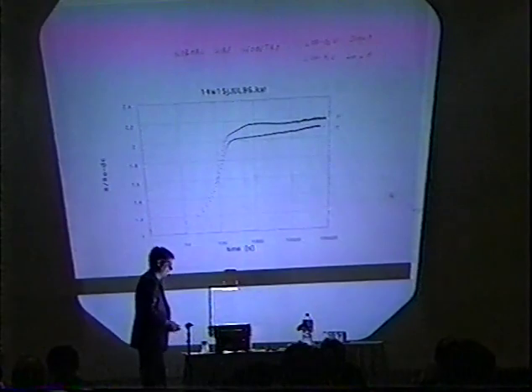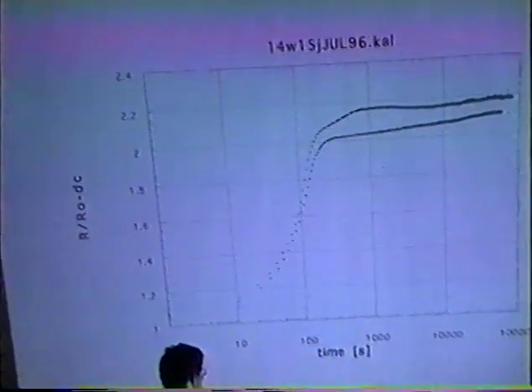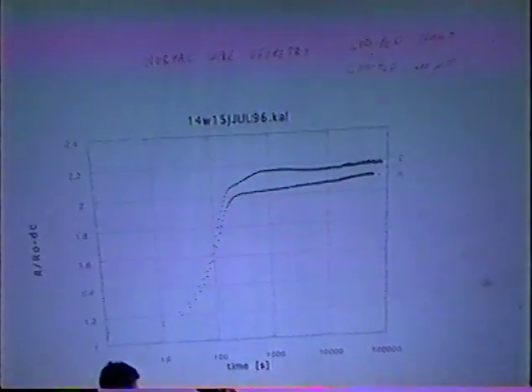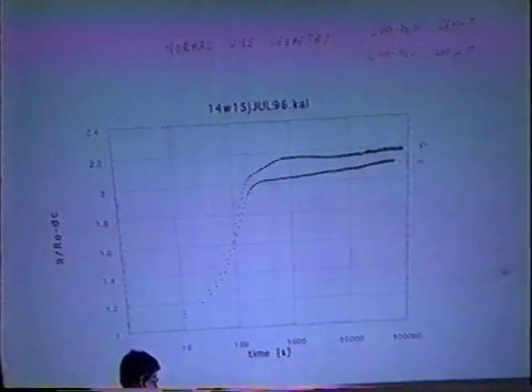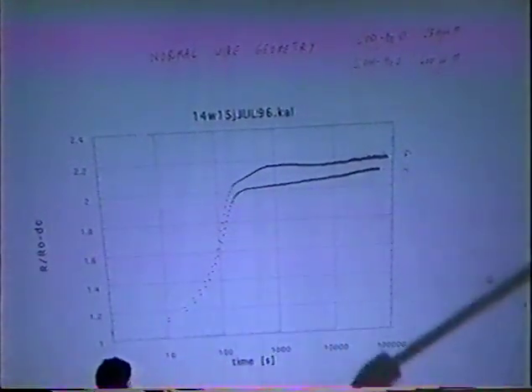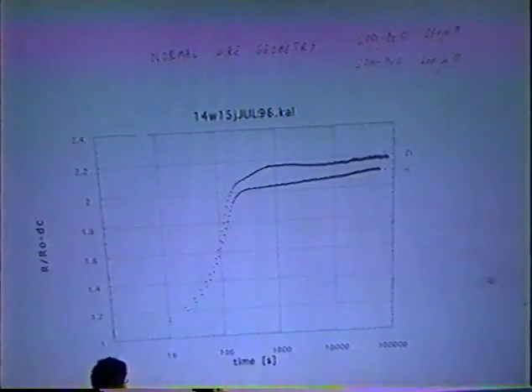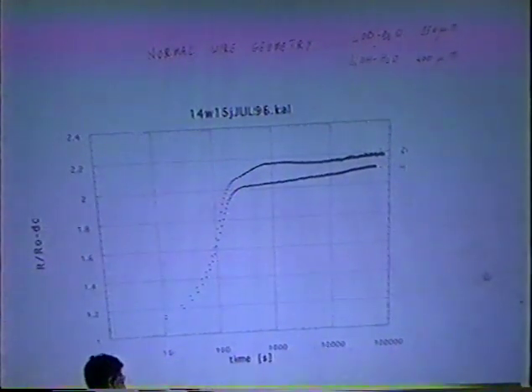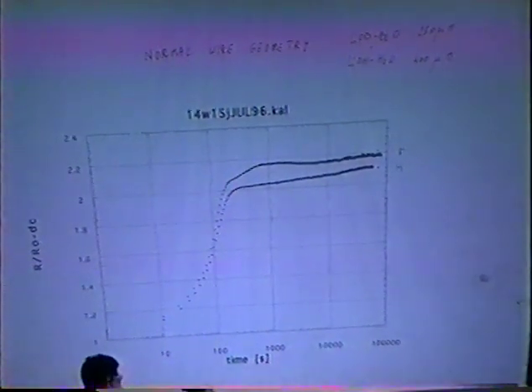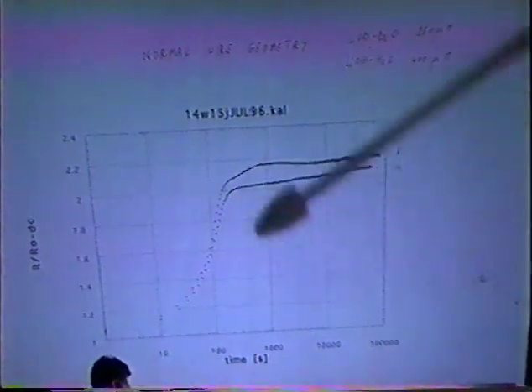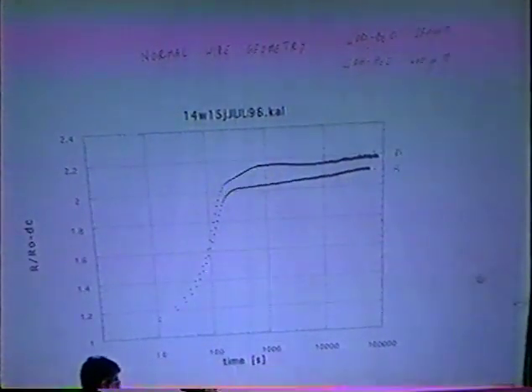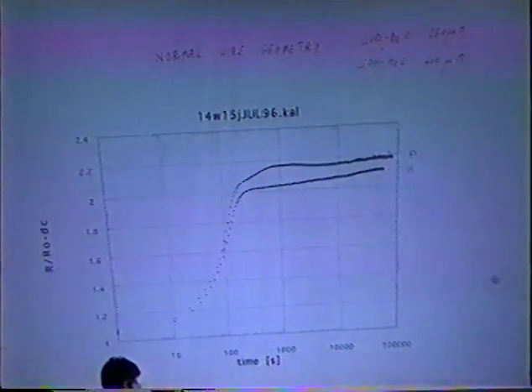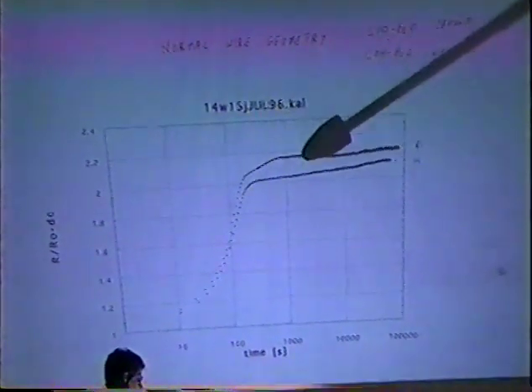These are the results using the normal wire geometry in the electromigration. Current 250 milliampere total current, means 50 amperes per square centimeter. This is the value and the hydrogen. We have the logarithm of time on the axis. The loading is extremely fast in comparison with pure palladium. Extremely fast. We never saw such fast loading in this material, and afterwards a slow increase.